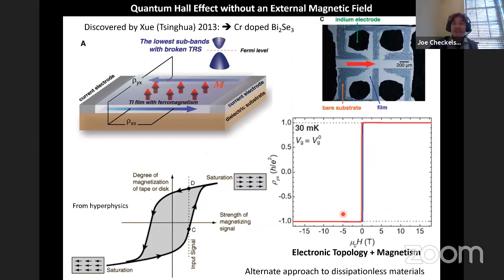Another way, and I think the real hallmark that people believe, is when your boundary mode, in this case a 1D boundary mode, is quantized, when its conductance is quantized in fundamental units of e²/h, it tells you that you're measuring the topological band index of your state, and that can tell you definitively that it has a topological origin rather than a trivial origin. You can actually have a co-mingling of these two types of surface modes, right? These are all excellent questions. Perhaps one of the reasons this experiment had to be done at very low temperature is that coexisting with these exotic surface modes were more conventional surface modes that needed to be Anderson localized by going to extremely low temperature. These are all really good questions.